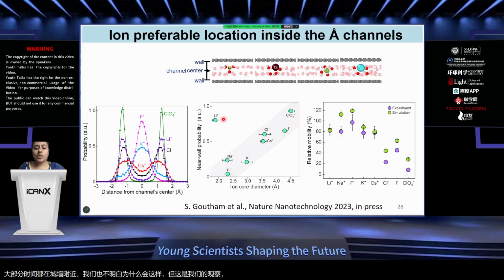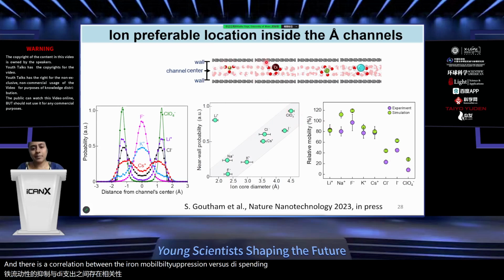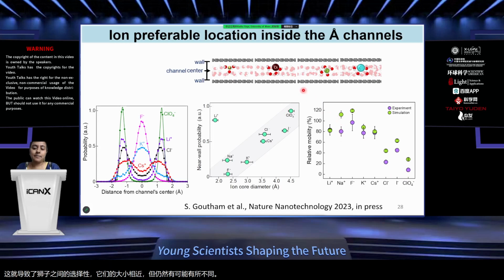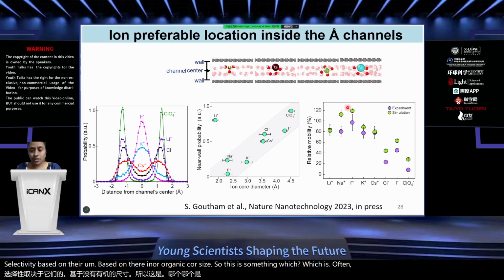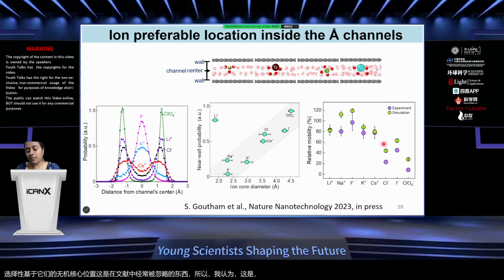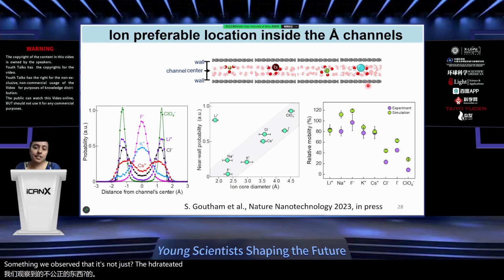And there is a correlation between the ion mobility suppression and the ion spending time near the wall. From our study, what we understand is that those ions which have very large core tend to travel along the walls, have some interaction with the walls, and that leads to their mobility suppression. So that leads to selectivity between ions which are close in size, based on their inorganic core size. This is something which is often ignored in the literature. It's not just the hydrated radius or hydrated diameter which is important, but also the inorganic core size.